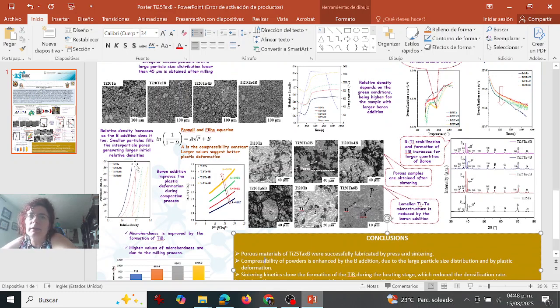Well, if we have a look at this graph where we have the pressure in megapascal versus the relative density, for the different samples with different percentages of boron added, we've seen that the relative density increases as the boron addition does too, and that the smaller particles fill the interparticle pores and generate a larger initial relative density.